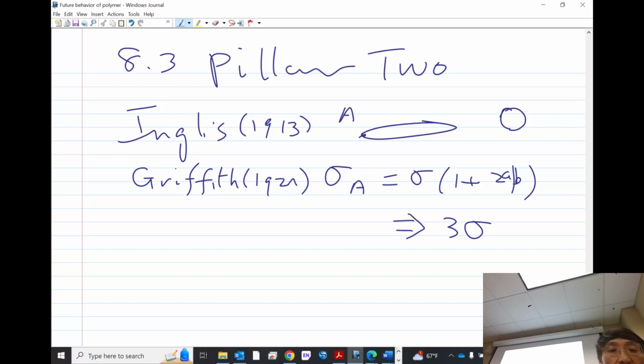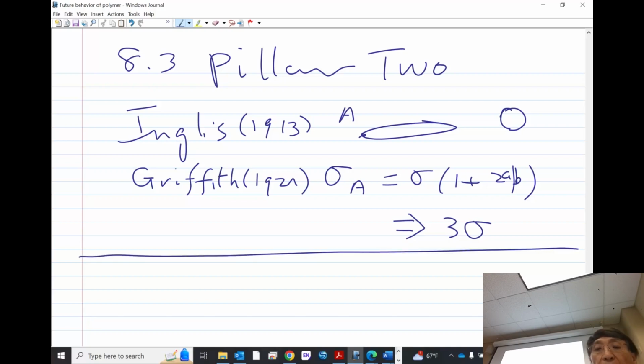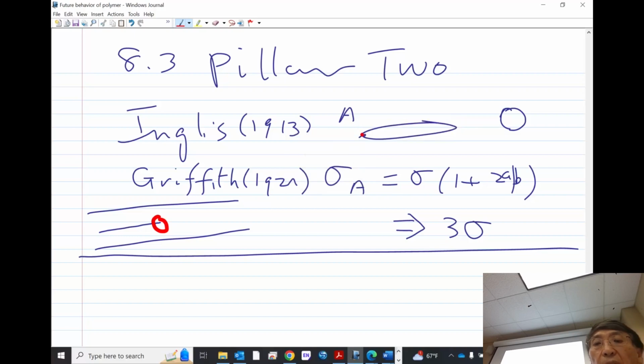Things continued. In fact, I failed to indicate to you guys that Rivlin and Thomas' paper, Pure Shear, is a remarkable paper. Not only did they identify this pure shear as an interesting way to look at toughness, they actually admit explicitly in black and white that they are not going to bother finding out what happened at the tip. Let me amplify this. In other words, the Inglis result just says if you sit at that pole, that's the stress.